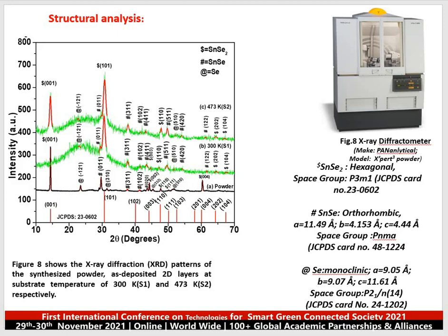Thus, we can say that S1 films showed absence of 001 orientation while demonstrating preferred orientation along the 101 plane. Moreover, the powder sample showed absence of the 101 plane and exhibits preferred orientation corresponding to the 001 SnSe2 plane. Besides this, the S2 films showed re-emergence of the 001 SnSe2 plane along with the presence of peaks that emerged in S1 films.